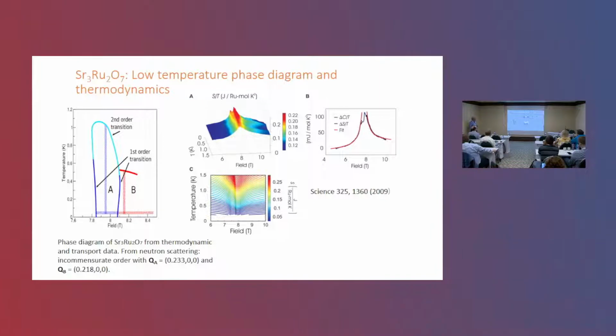Moreover, in thermodynamic measurements, these red lines of specific heat divided by temperature in a magnetic field were 1 over H minus HC, left and right. All these were puzzles. You don't expect in a good Fermi liquid this behavior unless something fundamentally different is there. And the phase diagram is that we have two different kinds of SDW, the A phase and the B phase, with slightly different Q vectors, but the difference is small, and this is measured along these hatched lines.